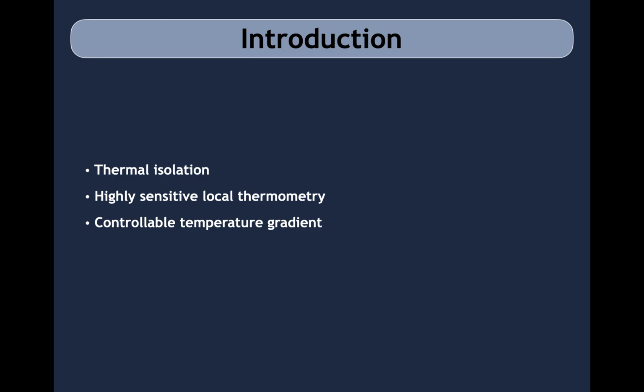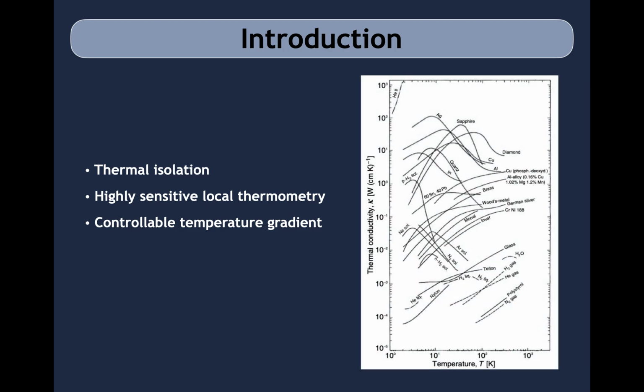The goal of this project is to use these three components and develop a dedicated thin-film thermal conductivity measurement platform for cryogenic temperatures, particularly below 1 Kelvin. While many materials have been measured at low temperatures, there is limited data for materials below 1 Kelvin, and this project hopes to help fill in that gap.